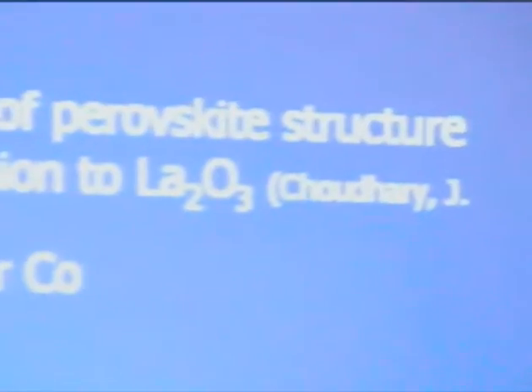Reduction at 300 degrees, we did low temperature reduction to try and avoid the reduction of the support happening between 400 and 500 degrees. So we did a low temperature reduction followed by reaction, and we still saw no activity. We also took this material up to 800 degrees, did pulsatile oxygen to try and see if possibly the metal had been covered by the support prior to doing reaction, and we saw no increase in activity.